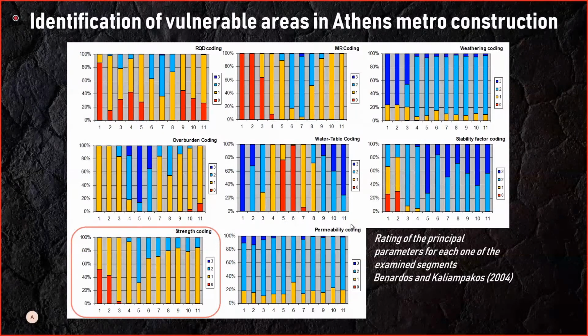For example, for the compressive strength of the formation, on the bottom left corner, we can see that the first two segments are characterized by rather adverse conditions, having values of 0 with a probability of occurrence around 40%, while the most favorable condition could be found on segment 5. However, even at this stage, it's really difficult to make a coherent assessment about the best and the worst areas that we can come up with.